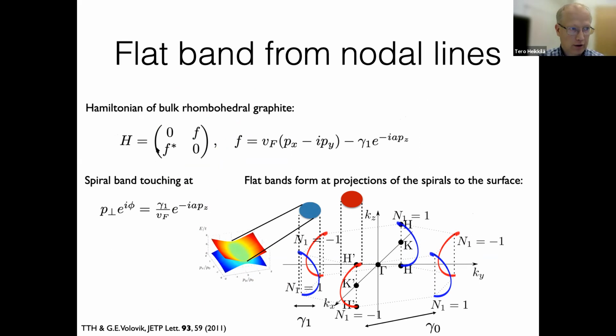You can write the Hamiltonian of bulk rhombohedral graphite, which is also a 2x2 Hamiltonian, and then this gamma 1 term comes here. And what you find is that in this case there is a spiral, so that there's a band touching at a given perpendicular momentum that depends on pz. In particular there are these spiral states, and this is a nodal line semimetal, which means that at every point on the spiral you have a Dirac point touching, and such nodal lines have a topological charge.